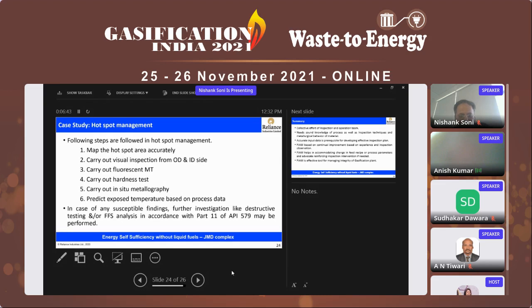The fifth one is in situ metallography. It is a tool to check if there are any changes in the microstructure of that specific element, which ultimately lead to a more degraded part. And in case of any susceptible findings, further investigation like destructive testing or fitness for service analysis will be carried out in accordance with Part 11 of API 579.